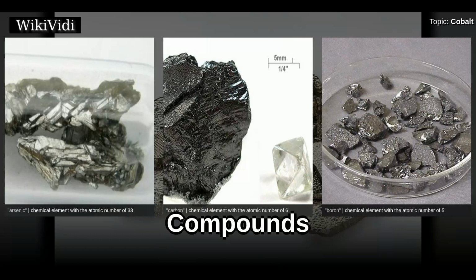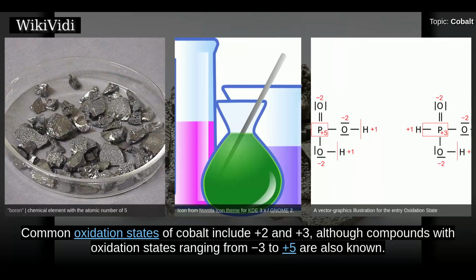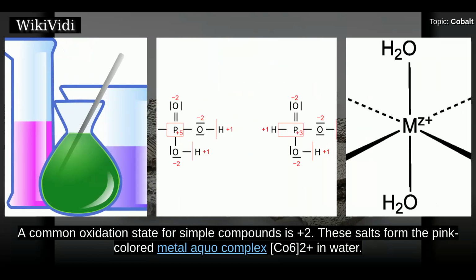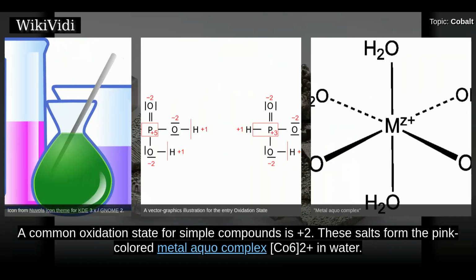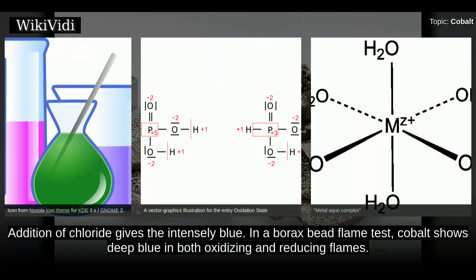Compounds. Common oxidation states of cobalt include +2 and +3, although compounds with oxidation states ranging from -3 to +5 are also known. A common oxidation state for simple compounds is +2. These salts form the pink-colored metal aqua complex, [Co(H2O)6]2+ in water. Addition of chloride gives the intensely blue [CoCl4]2-. In a borax bead flame test, cobalt shows deep blue in both oxidizing and reducing flames.